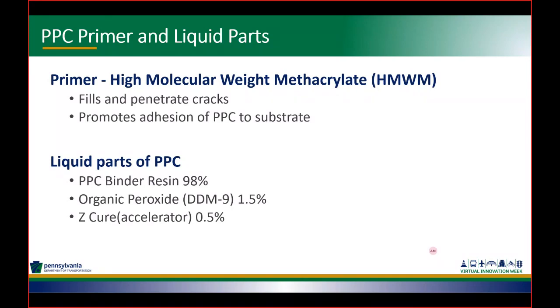So a little bit about the liquid parts. The primer: its purpose is mainly to fill the cracks and promote the adhesion of the treatment. Then the PPC itself is about 98% polyester polymer resin. And then we have 1.5% of organic peroxide, or DDM-9, and the accelerator. The last two, the DDM-9 and the accelerator, vary a little bit depending on the temperature. The manufacturer supplies tables, and depending on the placement temperature, you will tweak the DDM-9 and the accelerator.